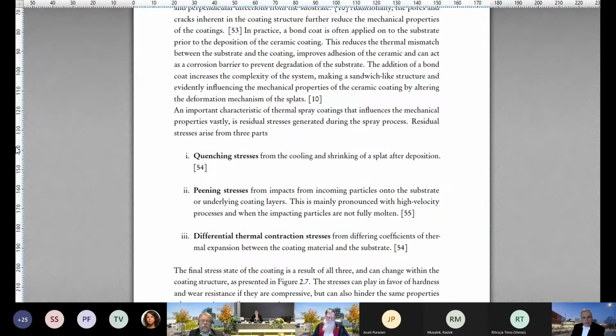I was thinking, like you said, do I recall right that there have been some experiments in adding some peening particles on purpose to densify the splats during the deposition? Would that be beneficial to close the cracks or something? As far as I recall, these are with metallic coatings, where you would add ceramic particles maybe to add the stresses and also improve the adhesion and cohesion. Yeah, you're right. It might not have much effect for the ceramic.